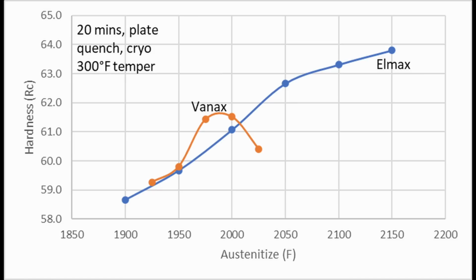I austenitized these for 20 minutes at the given temperature on the chart. Then we did a plate quench, and I used liquid nitrogen cryo, and then I tempered at 300 degrees. You can see that for Elmax, we have a wide range of austenitizing temperatures where we can get 61 plus Rockwell. And if it was higher than 61, we could temper it down to a lower hardness. So temper it hotter and get lower hardness.